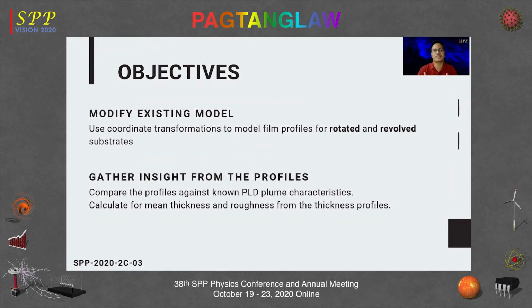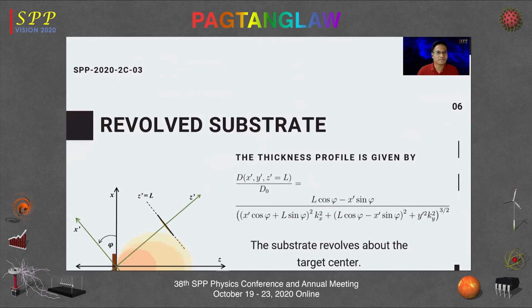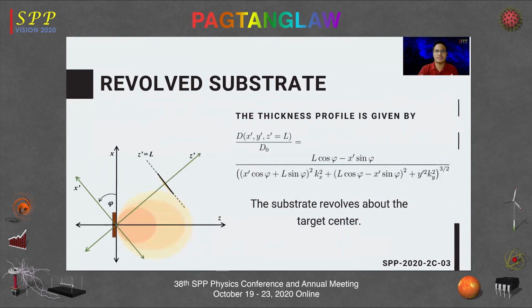We want to use coordinate transformations to model film profiles for rotated and revolved substrates. We want to compare the profiles against the known PLD plume characteristics, and we want to calculate the mean thickness and roughness for the thickness profiles. For the revolved substrate, this is the equation that we have derived upon coordinate transformation. Upon coordinate rotation, the substrate effectively revolves about the target center. And this is the equation that we have derived for the thickness profile.